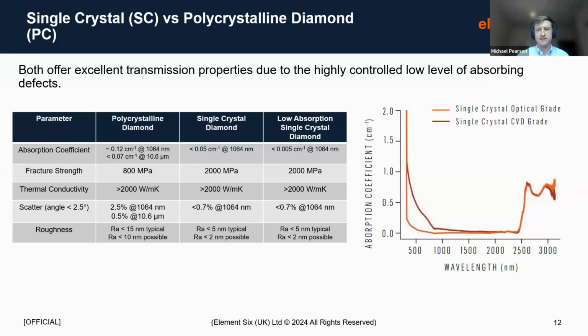On the right hand side there are examples of two different grades of single crystal diamonds. So our standard single crystal CVD grade and our low absorption optical grade diamond. If I were to overlay polycrystalline diamond on that, what would I expect? I would expect less transmission in the short wavelengths, so in the visible, for example, and that's not actually absorption that's causing that. It's predominantly scatter. And that scatter is a consequence of things like grain boundaries and other very small defects that are present in the polycrystalline material. If your application is actually at a relatively long wavelength, so 10.6, I've talked a lot about that CO2 laser wavelength.